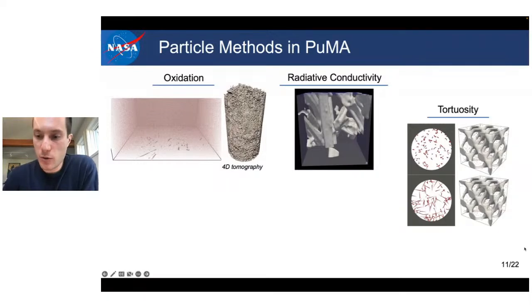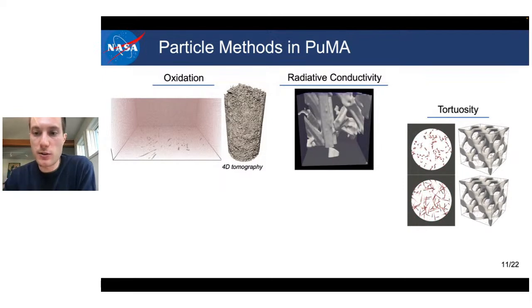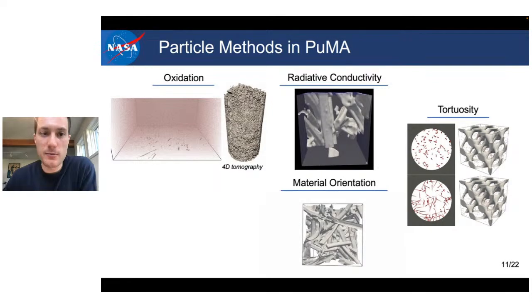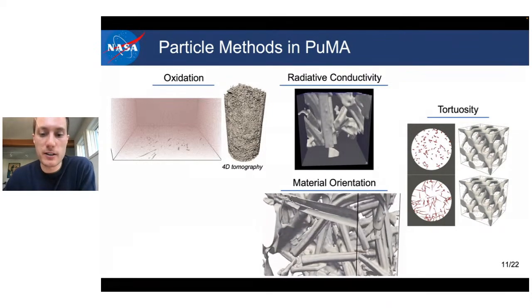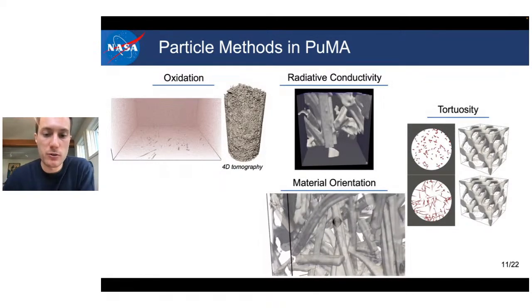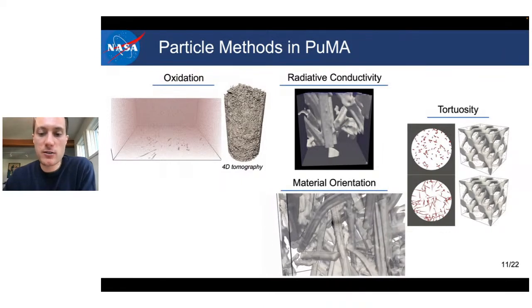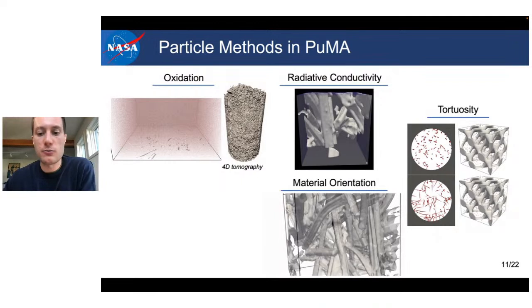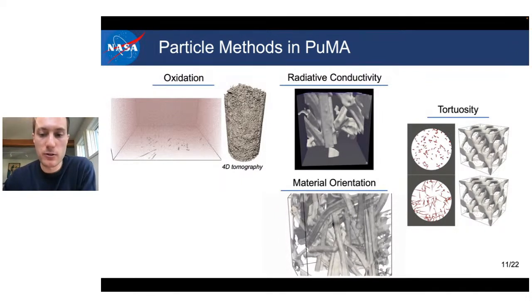Another thing that we can compute is the tortuosity. We can track how these particles travel through the material, through the microstructure. And by checking how tortuous their path is, that's also correlated to the tortuosity at different regimes. And in fact, here you're seeing different Knudsen regimes for different rarefied environments. We can also use the particle method to compute the material orientation, and in fact, this is one of the 3 ways that you can compute it. You can scatter particles in every direction and track the one that travels the longest, and that's roughly aligned with your local material orientation.